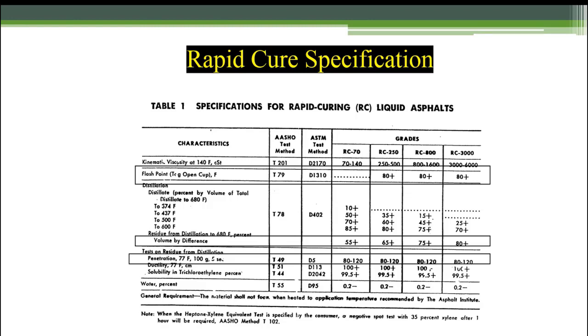So the key takeaway there is that the viscosity has its advantages, but you have to shoot more of an RC70 to get the same amount of asphalt compared to an RC3000. The other thing, the last point down below there, was penetration. You can see the residual asphalt itself was all 80 to 120 pen graded asphalt. So that's a mid-type softness asphalt. I bring that out here because we're going to talk about emulsions as well.